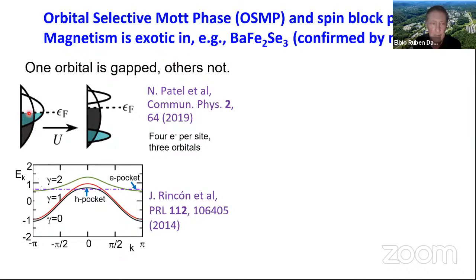And suppose that you have two orbitals. This is the density of states. And one orbital is narrow compared to the other one. And suppose that they are shifted a little bit by crystal field. So what happens when you introduce U, the Hubbard U? When you introduce the Hubbard U, the orbital that is the narrowest is the most affected with increasing U. And there are many cases, this is not a pathological situation, it occurs often, that there is a gap opening in one of the orbitals and the other one remains gapless. You can consult this publication to see the actual density of states, which, as you can imagine, is a bit more complicated than the cartoon.